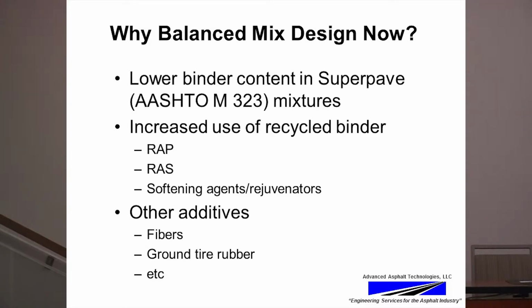There's also been an increase in the use of recycled binder. Lots of recycled materials are being used: recycled asphalt pavement, recycled asphalt shingles. These are sometimes used in combination with rejuvenators and softening agents. With these types of mixtures, you really cannot assess their performance based on binder properties and volumetric properties alone.